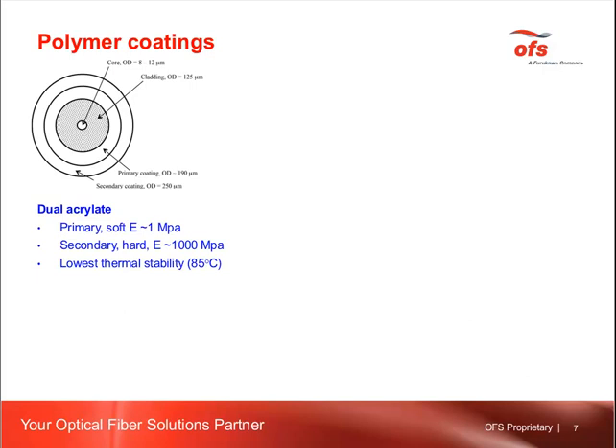Most common telecom-grade fibers have dual acrylate coatings with a soft primary with a Young's modulus about 1 megapascal and a hard secondary coating with a Young's modulus about 1 gigapascal. The role of the primary coating is to cushion possible microbends. Such coating typically is rated to temperatures about 85 degrees C, which follows from the data sheets of most producers